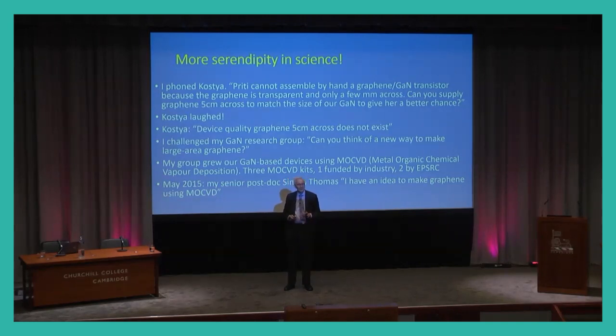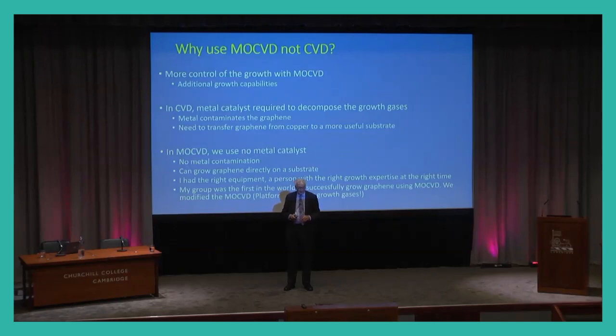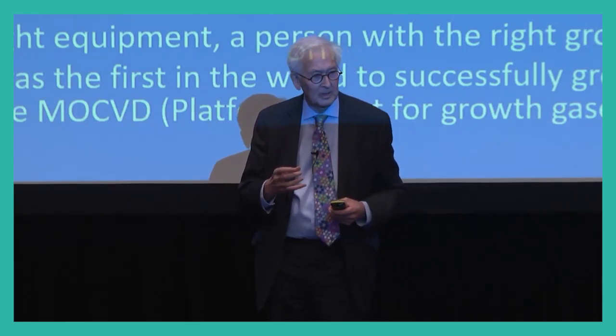Now, you may think that's a pretty obvious thing to say, but actually, it wasn't obvious because for making inorganic materials, the standard method was CVD, chemical vapor deposition, and MOCVD was only used if you had metals in the gaseous precursors. So when we grew gallium nitride, we used MOCVD because of the metal. But MOCVD is a growth technique which not only uses metal precursors, it's much more sophisticated than CVD. So a CVD equipment may cost up to £200,000. MOCVD is £1 to £2 million, right? It's very much more sophisticated.